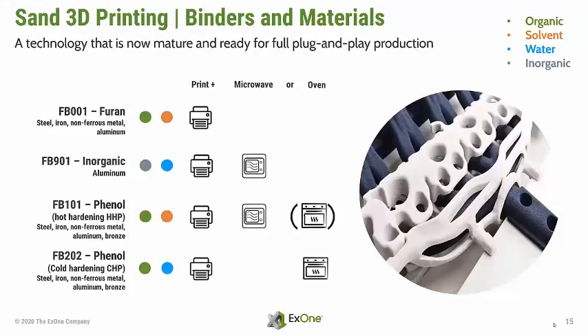We are offering 4 different binder systems to support different metal and casting applications. More than 80% of the business runs with the organic Furan binder. The high achievable core strength of Furan makes it suitable for applications from aluminum up to steel. As the parts are curing right after the print, they can get harvested from the job box without an additional curing step.